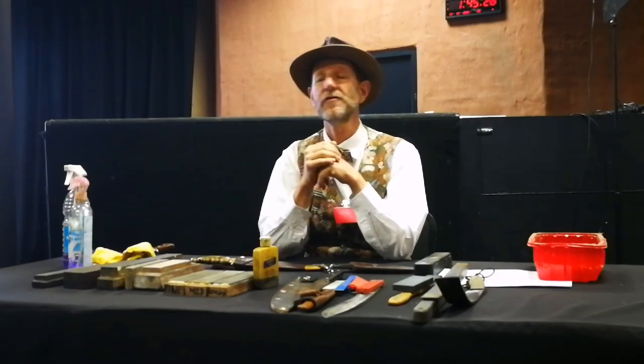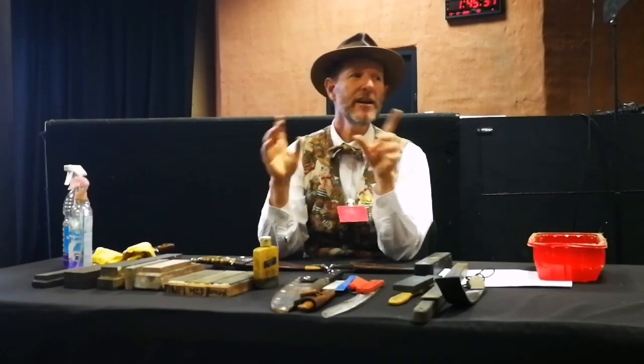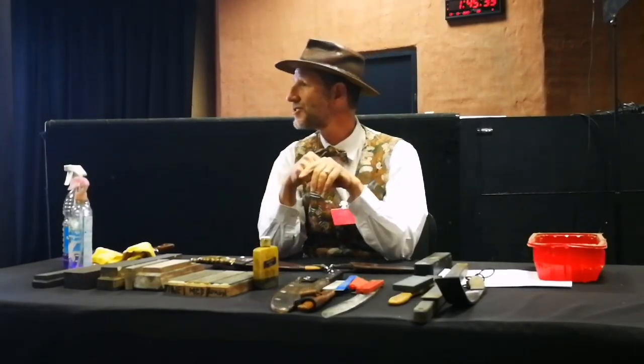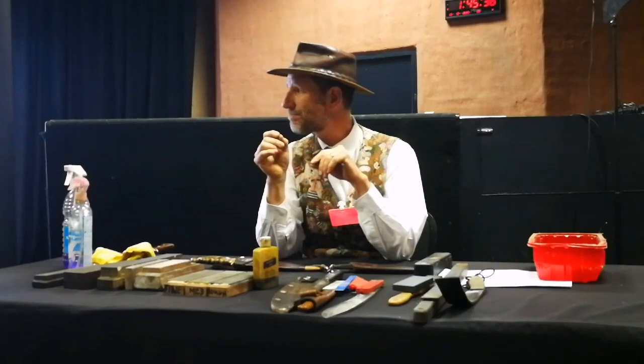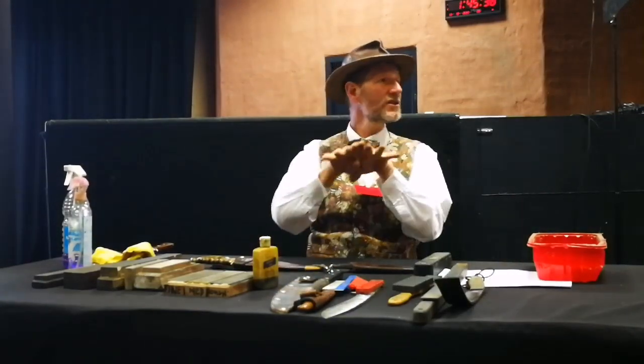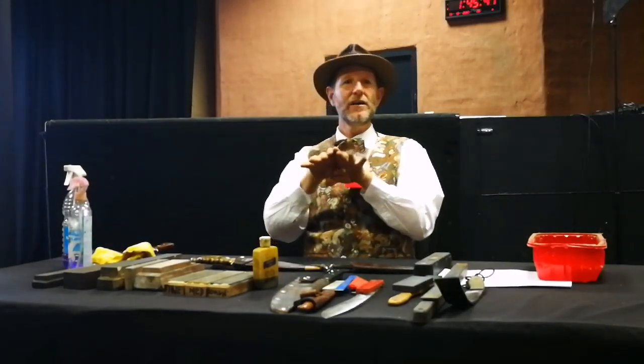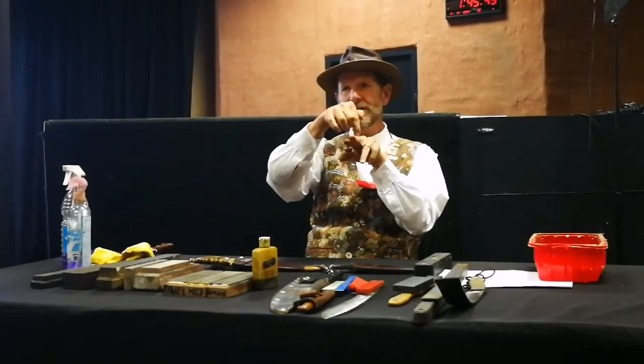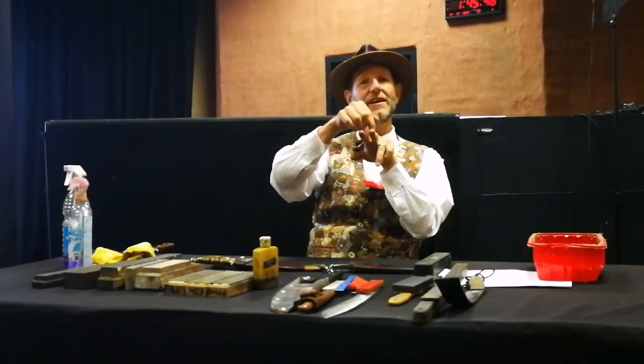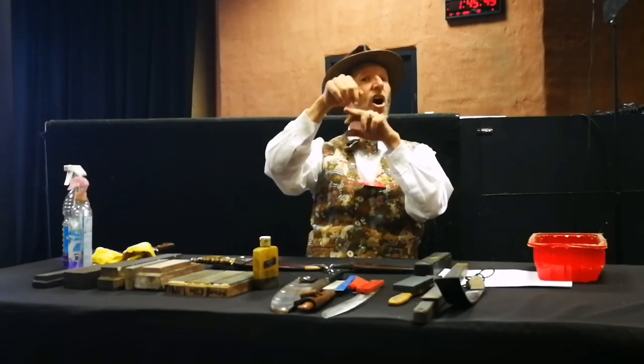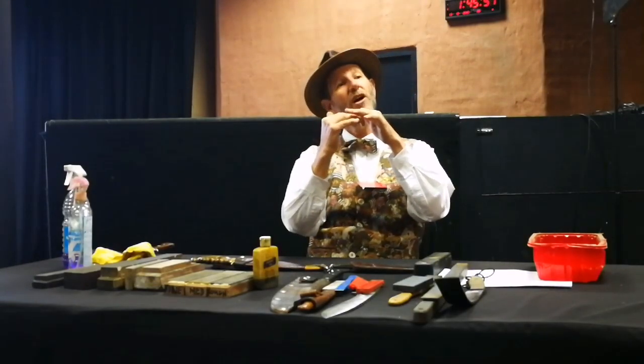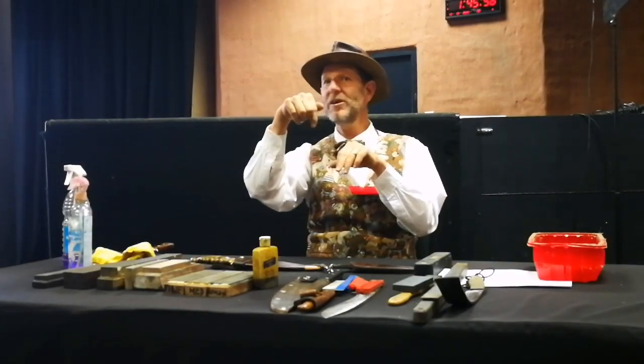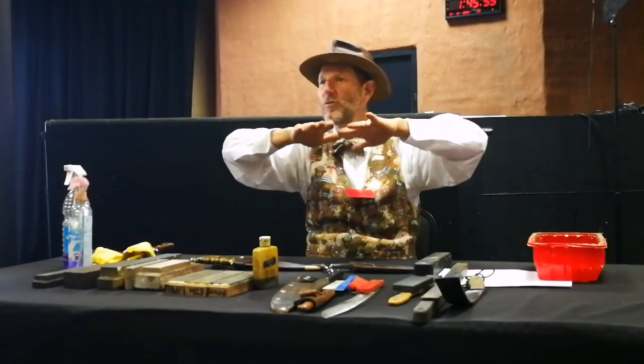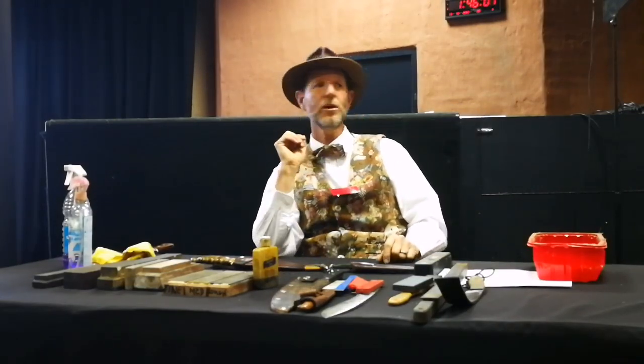Now, if you've got a Damascus blade, you can't really rely on the Rockwell hardness test as a true measurement of hardness, because the Damascus contains multiple layers. Depending on which layer you land on, you might be pinpointing the hardness on one layer. It might be a hard layer just on top of a slightly softer layer. So as you put the diamond on, the underlying layer will give a little bit. So measuring Rockwell on Damascus blades is not entirely reliable.